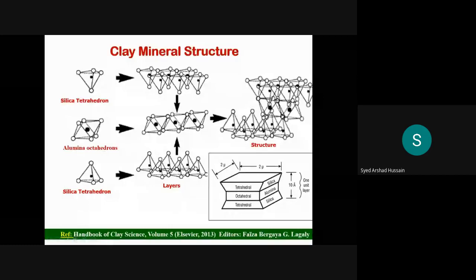And the layering of silica and alumina sheets together, the ratios are like this: one silica layer to one alumina layer, that means one layer; two silica, one alumina, this is another layer. And this is schematically shown. This is the silica tetrahedron, this is the silica layer, this is the alumina octahedron, this is the alumina layer, and layering upon this forms this kind of structure, and repetition of this structure forms the crystals.